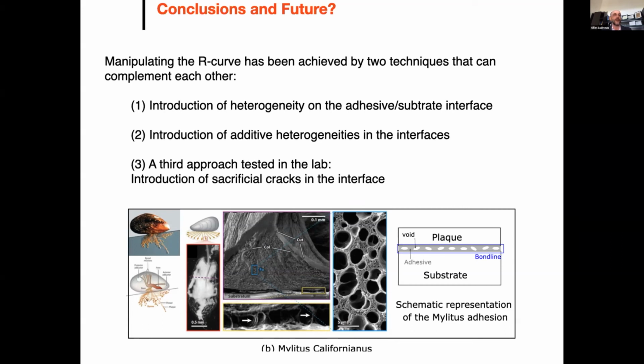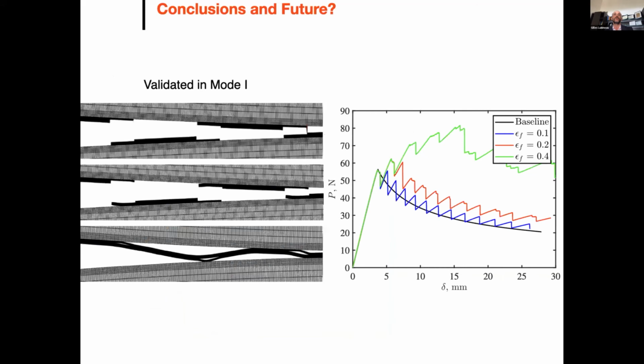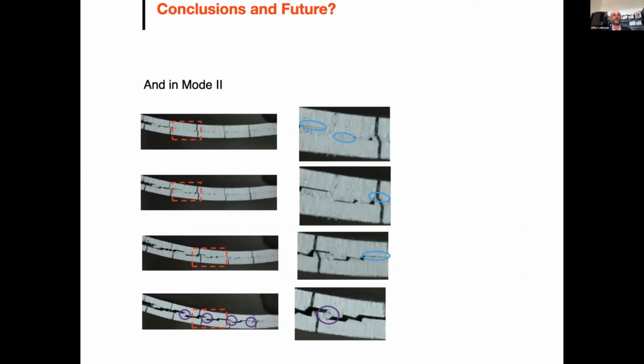So this is inspired more from biological adhesion systems, in which when you look at the adhesive bond line of a biological adhesive system, you have a lot of micro voids that are there to promote the dissipation of energy, and thereby to increase the effective toughness of the system. And this is something that we do in the lab by introducing sacrificial cracks in the adhesive bond line. And here again, you have an additional step of performance coming, because you can create multiple fragmentation inside the adhesive bond line by doing these kinds of things. And this is a third promising path.